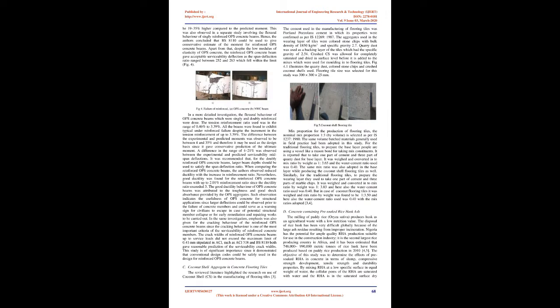Interestingly, the experimental ultimate moments were found to be 19 to 35% higher compared to the predicted moment. This was also observed in a separate study involving the flexural behavior of singly reinforced OPS concrete beams. Hence, the authors concluded that BS 8110 could be used to give a conservative estimate of the moment for reinforced OPS concrete beams.